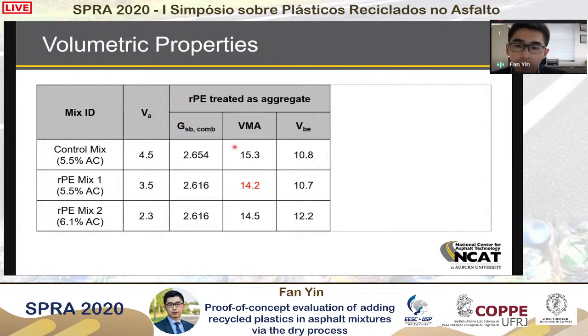In this case, if we look at the VMA, all these calculations in the middle part of the table, we are treating the plastic as aggregates. And then we adjust the Gsb number of the combined aggregates. And then we do the calculation for VMA. In this case, the VMA also dropped by 1%. And if you take the difference between air void and VMA, we get the VBE. And those two numbers are pretty much the same, which makes sense since we did not change any binder content in the mix, and there was no binder absorption difference. So that's why they have very similar VBE numbers.